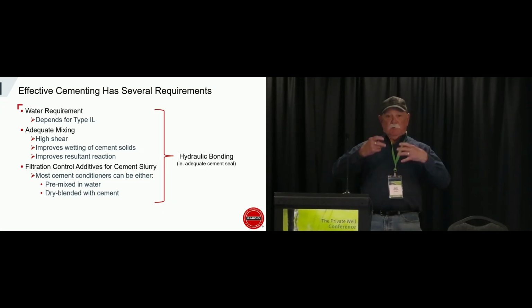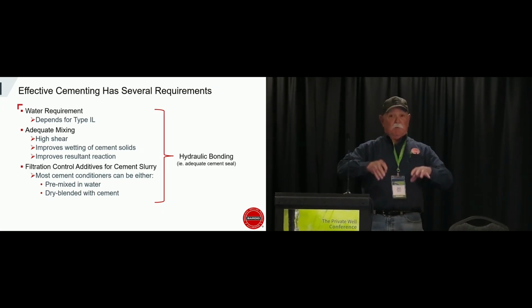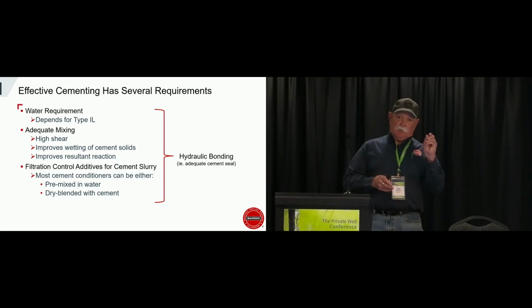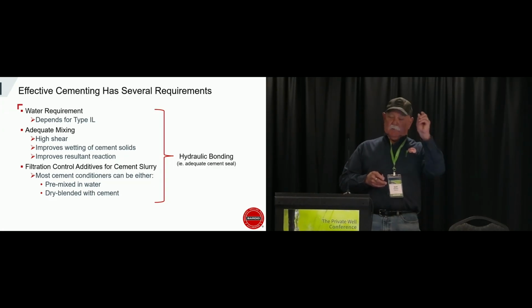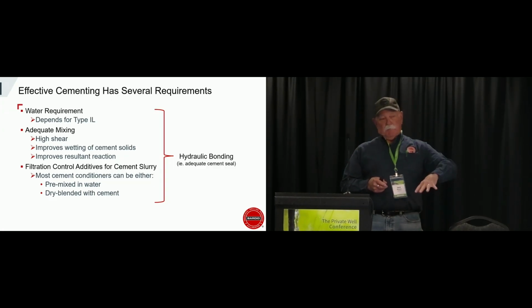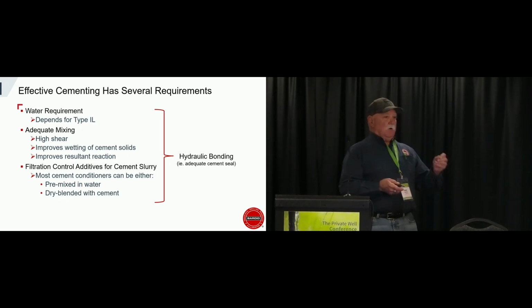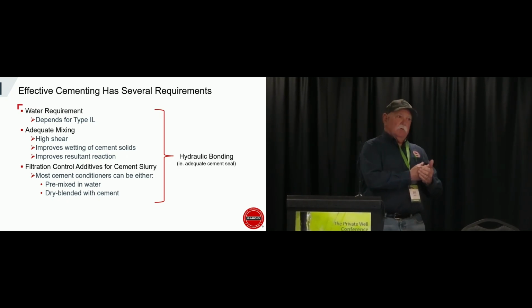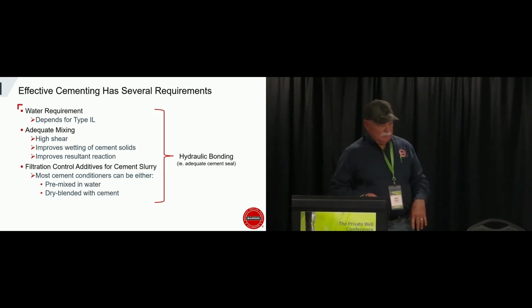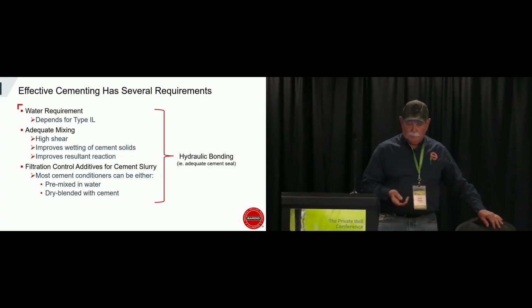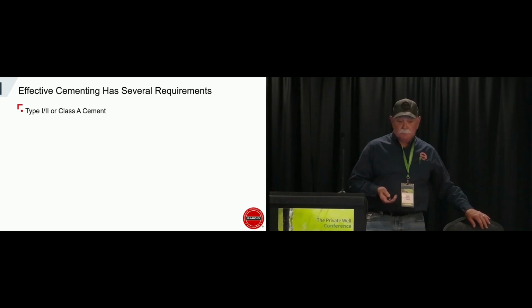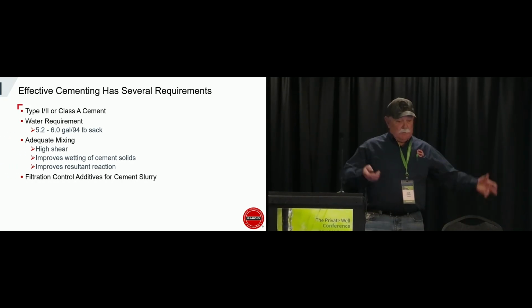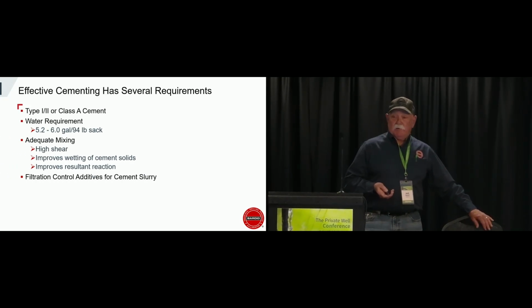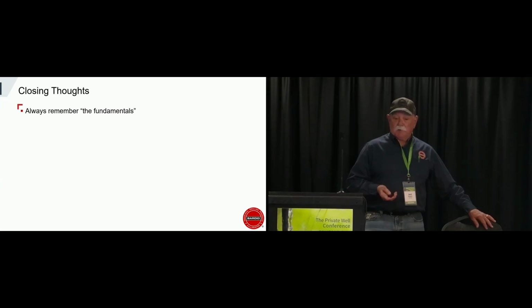So basically, we talked in the beginning about the drilling method. When you're drilling, you create what we call filter cake on the borehole. If that's not removed and you try to cement, then you're not going to get a cement borehole bond. So it's important that you do the drilling process properly as well. So here we go. What we recommend is 6 gallons of water per 94-pound sack of cement, and of course, proper equipment for mixing everything.